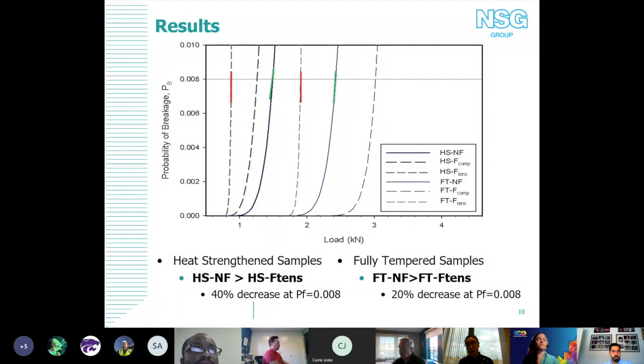And yeah, it's a lot closer whenever you get down to probably a failure of 8 in 1,000, but we're still seeing a 40% decrease in heat strengthened glass and a 20% decrease in fully tempered glass once you start putting that fritted side in tension. In some of the tests that we did, we actually saw that the glass was fracturing at a stress lower than the recorded residual stress that we measured, which means that potentially the residual compressive stress on the fritted side isn't as high as it would be on the unfritted side.